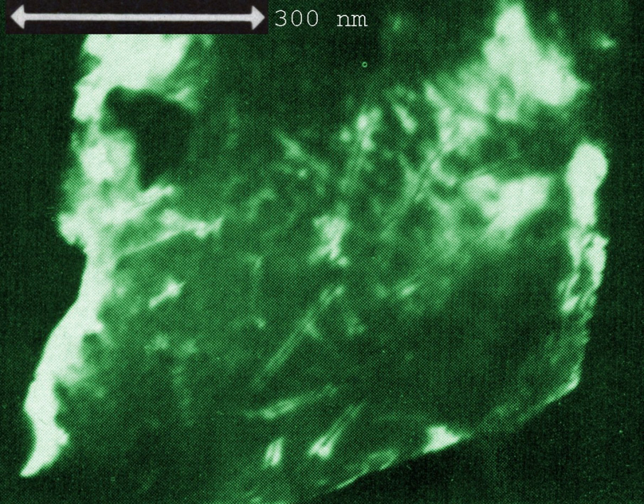Topic: Materials susceptible to ion track recording. The class of ion track recording materials is characterized by the following properties: high homogeneity, local density variations of the pristine material must be small in comparison to the density deficit of the ion track core. Optically translucent materials, such as polycarbonate and polyvinylidene fluoride, have this property. Grained polymers such as polytetrafluoroethylene do not have this property.